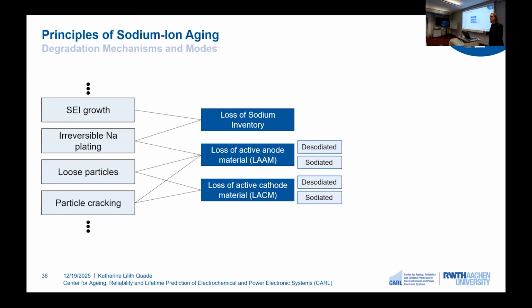And we can have loss of active material in two states, in the desodiated state and also in the sodiated state. And for the sodiated state, this means that we lose electrode capacity that was sodiated, so we also lose sodium. And we now want to analyze in which category, which degradation mode is most prominent.